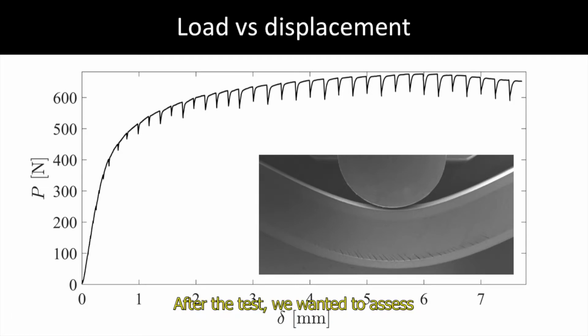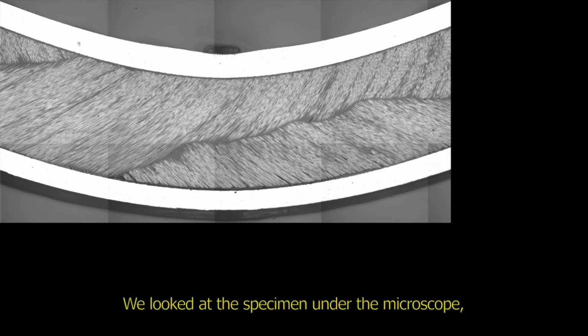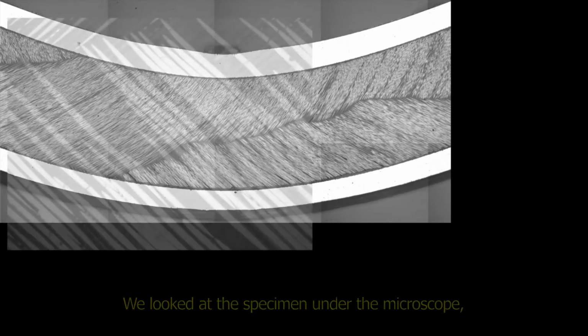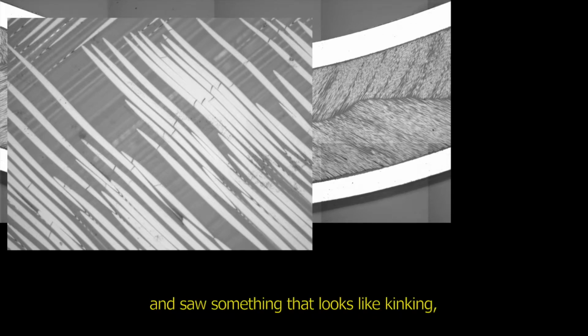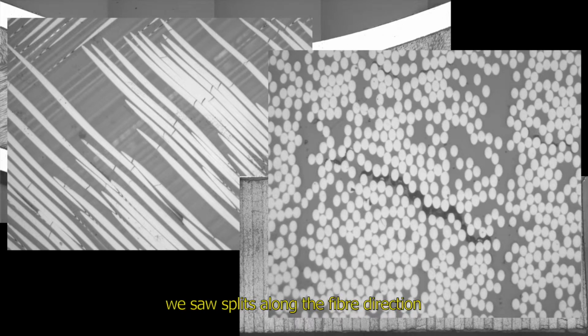After the test, we wanted to assess the damage in the microstructure. We looked at the specimen under the microscope and saw something that looks like kinking, a feature commonly associated with compressive failure. And in the other direction, we saw splits along the fiber direction, but these splits don't extend across the ply interfaces, and there is no delamination between the plies.